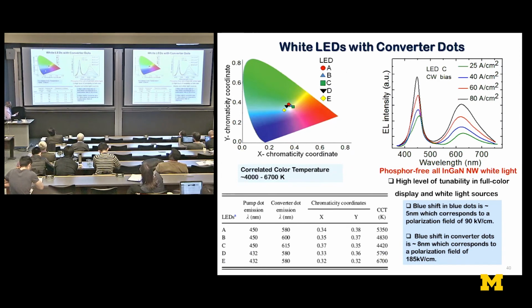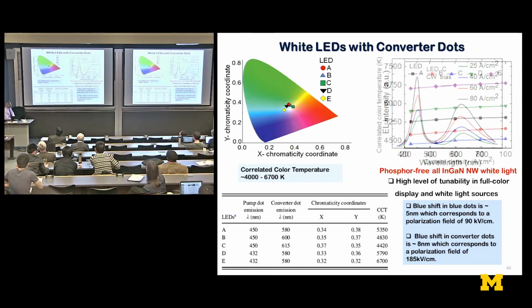And you can vary the chromaticity coordinates and therefore the correlated color temperatures. And we can go all the way from warm to cool temperatures, and we didn't go further. And now, they were very excited with these results, and we could go even below. We know we could go even below 4,000 to go to true warm colors. And so now they are following this up themselves at Regensburg.